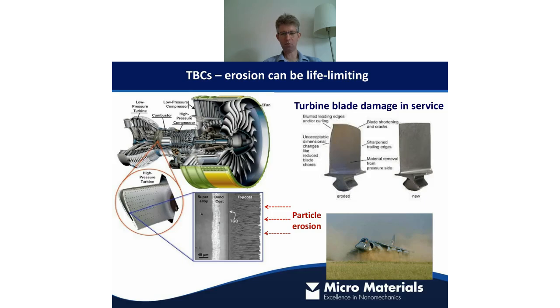So this one shows a more detailed example of one of these systems. But the downside is that in the engine, these thermal barrier coatings that protect the turbine blades are susceptible to a certain amount of particulate erosion, be it sand particles typically. That can be worse in dusty environments, but equally, even in any environment, there can be sand in the engine, gets ingested. And eventually it can lead even to dimensional changes in the blade, and under some cases, it can even be life limiting, essentially. So you can have an engine failure, and that obviously can have catastrophic consequences.